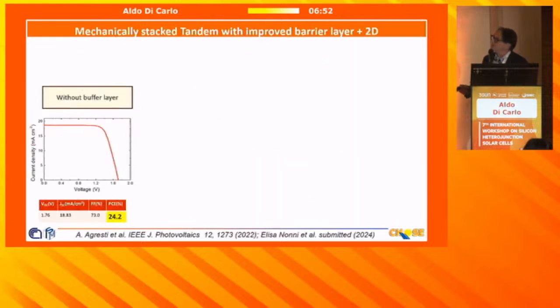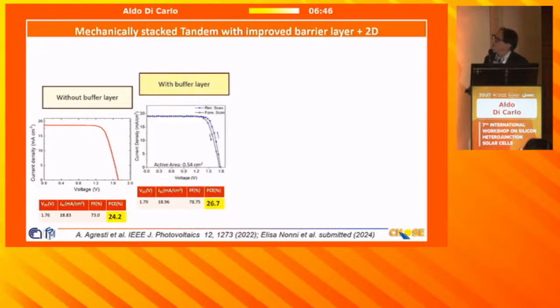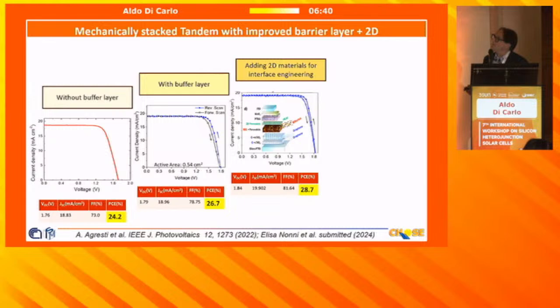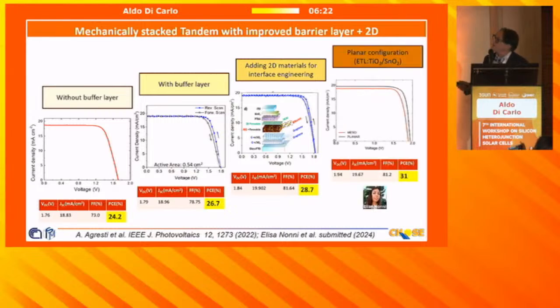Let me show. We started some years ago with 24%. Then we improved by adding the buffer layer to get a better ITO. Then we added 2D material to change the interface properties and adapt better the work function of the layer, and we used graphene and also MXenes inside. And then we moved from mesoporous to planar architecture, and these are the latest results we are trying to communicate. So we can get 31% by using this very simple way to do the tandem architecture, which you can do any time in your laboratory.